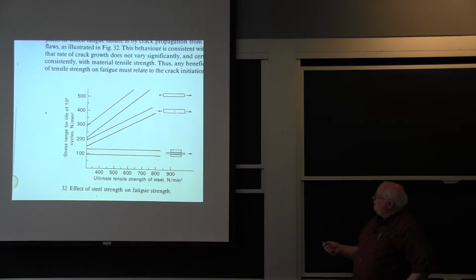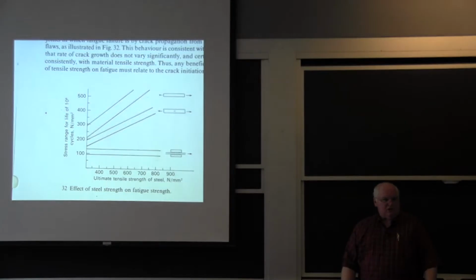If you put a hole in it, so I have a stress concentration, the stress concentration lowers the fatigue strength, and it lowers it proportionally more for higher strength steels than for lower strength steel. It's not quite a 45 slope. If I put a weld in it and I load it transverse to a fillet weld, I get no benefit from strength, okay, in fatigue.